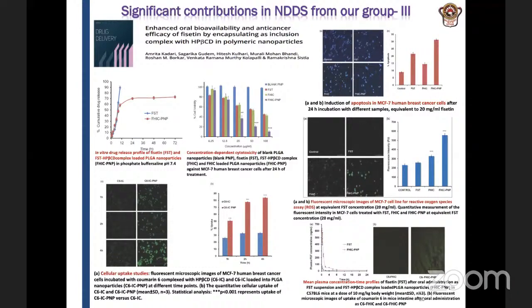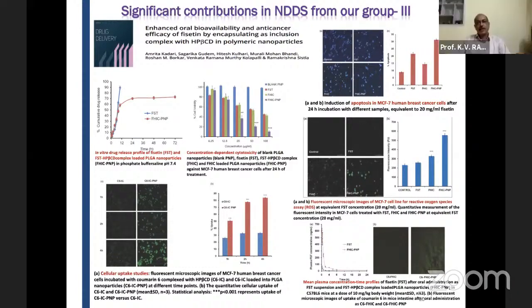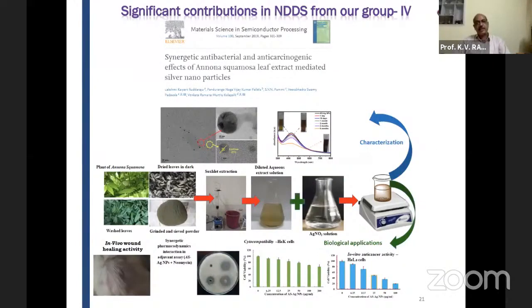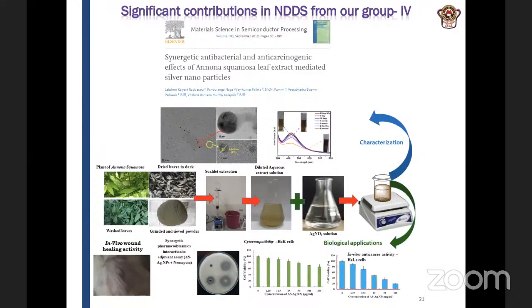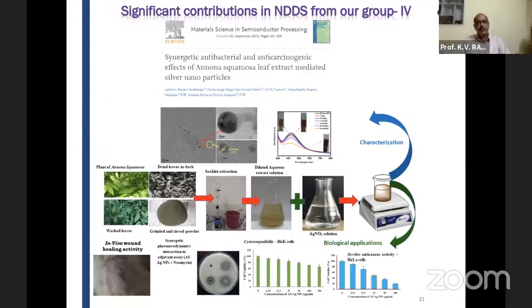And we wanted to test the antibacterial activity of these metallic nanoparticles as well as their anti-cancer activity. The majority of these metallic nanoparticles are made using very corrosive approaches, with hard chemicals for causing the reduction of these metals for formation of the nanoparticles. We wanted to prepare the nanoparticles using a green synthesis approach, wherein we tried Annona squamosa leaf extract, which is used as a reducing agent.